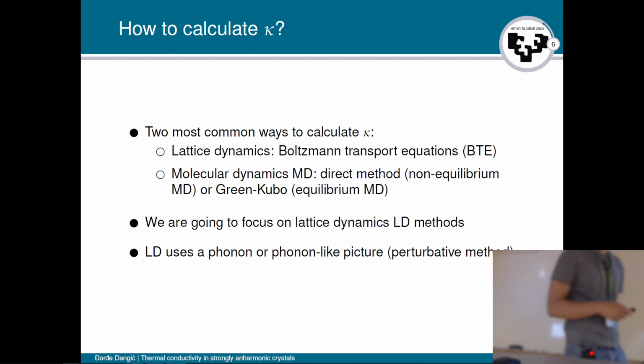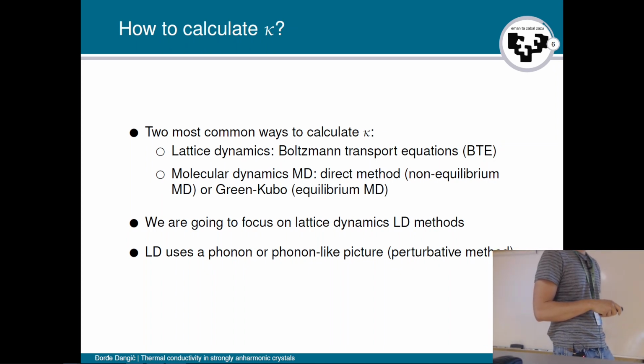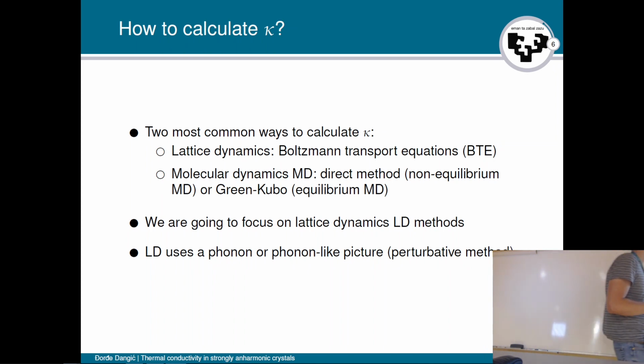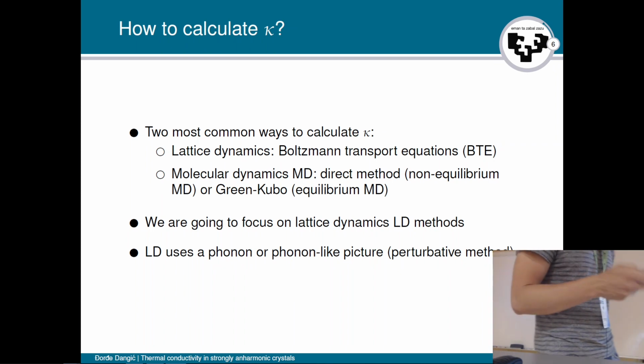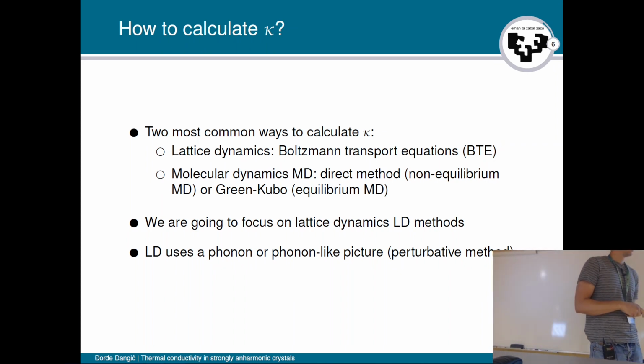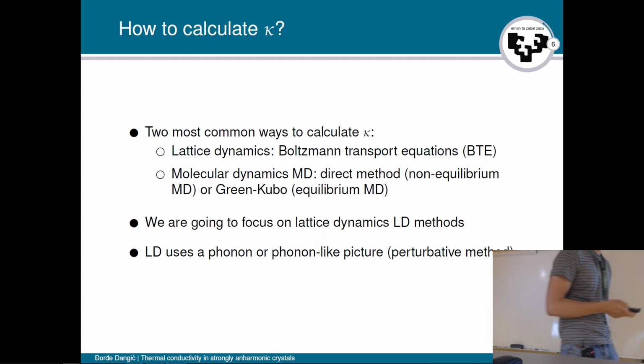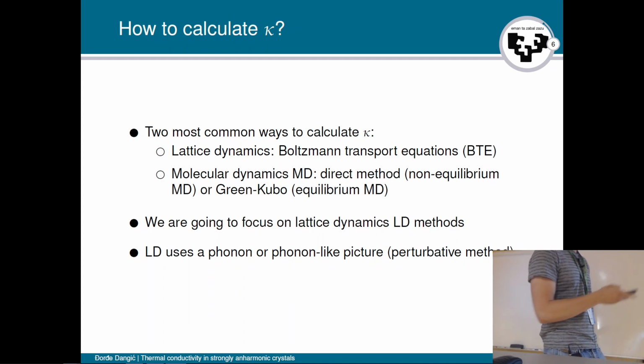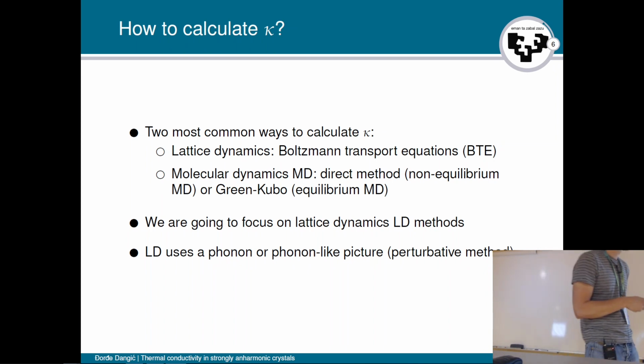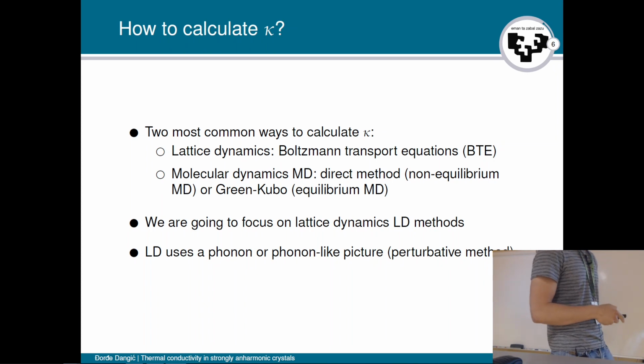So as I said before, we are going to focus on the lattice dynamics method. What I mean by lattice dynamics method is basically using a phonon or phonon-like picture. So you take your Born-Oppenheimer energy surface, you expand it in the Taylor series, and then you do the perturbation theory or whatever to actually get the heat current and calculate lattice thermal conductivity. Okay, so as I said, when we do lattice dynamics, we use the Boltzmann transport equation to calculate lattice thermal conductivity. And this is actually now implemented in SSCHA. So let's briefly discuss this method.